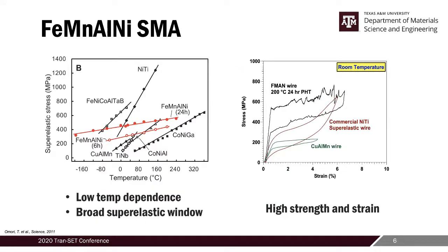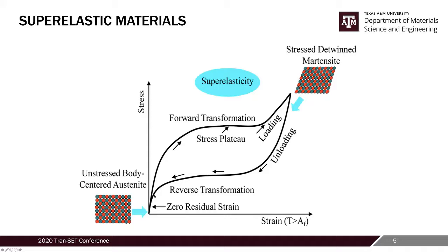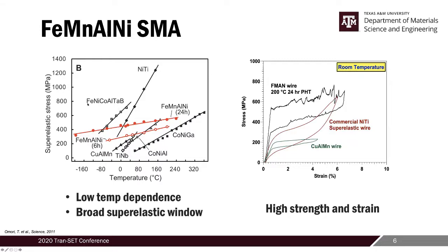And there are lots of different iron-based SMAs, but for this project, we selected iron manganese aluminum nickel SMA, and the reason is because of this graph here on the left, which shows the superelastic stress levels versus temperature. Superelastic stress levels correspond to the stress at which this material transforms. Here you can see iron, nickel, cobalt, aluminum, tantalum, boron, or copper, aluminum, manganese, or nickel titanium alloys. But our composition here, which is shown in the red line, is iron manganese aluminum nickel alloy.